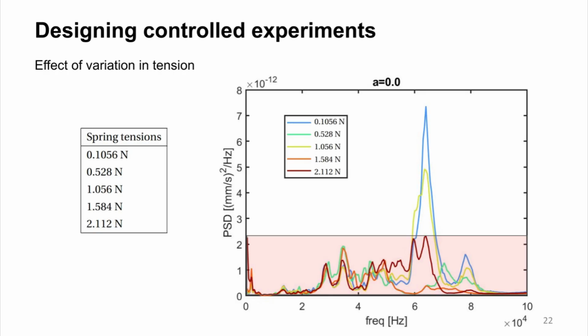I tried 5 different tensions, and for the least perturbed or unperturbed point cloud, a network generated from that point cloud, I saw that the Bragg peak around 63 kilohertz gets non-monotonically attenuated or amplified depending on the tension under which I held my metamaterials. As you can see, for the lowest of the tensions, which is 0.1056 newtons, my Bragg peak is highest, whereas for the second lowest, it has completely vanished, but then it reappears for the third, and so on and so forth. So it has a very non-monotonic behavior under tension.